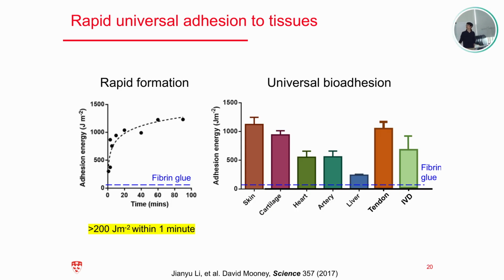And let me quickly show you more detail about the adhesion performance. Because we are leveraging a variety of interactions, electrostatic and chemical bonding between the adhesive and the tissue, we can form adhesion pretty rapidly. Within 1 minute, we got 200 joules per meter squared. This chemistry targets quite universally the proteins of biological tissue, so it's universally applicable to different kinds of tissue: skin, cartilage, heart. In my lab, currently we are focused on the intervertebral disc or the cartilage. They all achieve a very high adhesion energy, much higher compared to the clinically used fibrin glue.